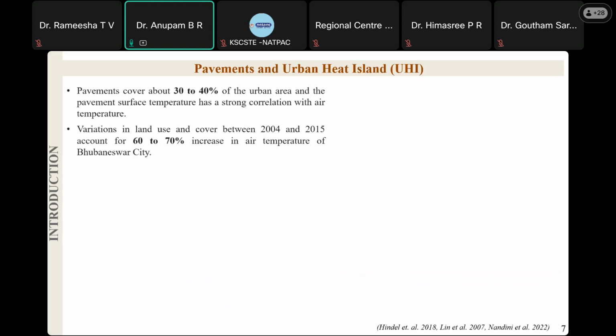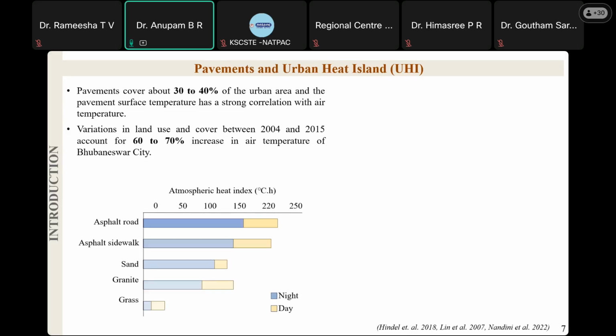Pavements contribute to urban heat island because pavements cover about 30 to 40% of a city by area. If you see the top view, 30 to 40% of the urban area is pavements. And evidence from Bhubaneswar city shows that about 60 to 70% of the temperature rise of the city from 2004 to 2015 was caused by variation in land use and land cover. If you take the case of Bhubaneswar city, up to 70% of the temperature rise experienced by the city in the past 10 years is due to the change from natural vegetation to artificial structures, both asphalt and concrete and buildings. That's mainly because the heating index of these materials is much, much higher than natural materials like sand and grass. They heat the surroundings much more than natural materials.